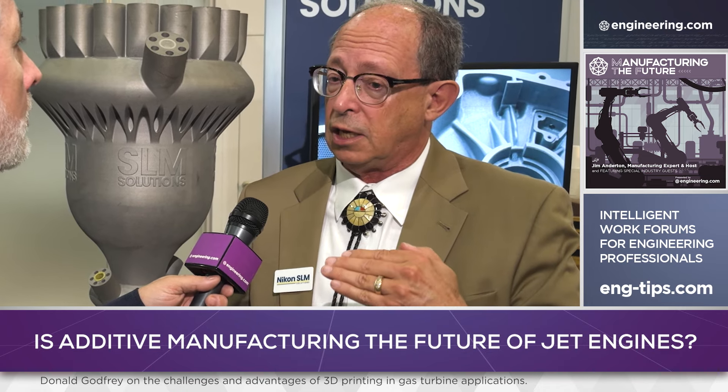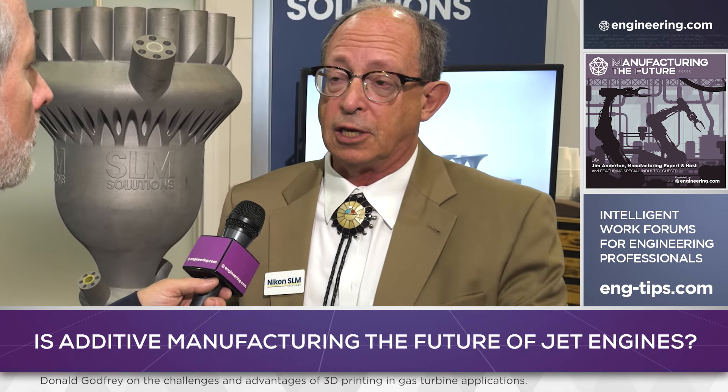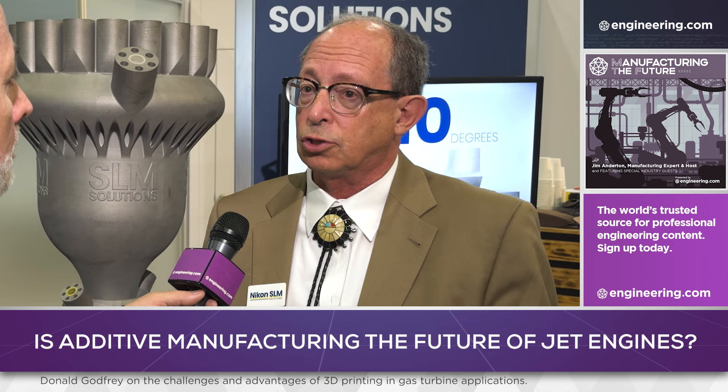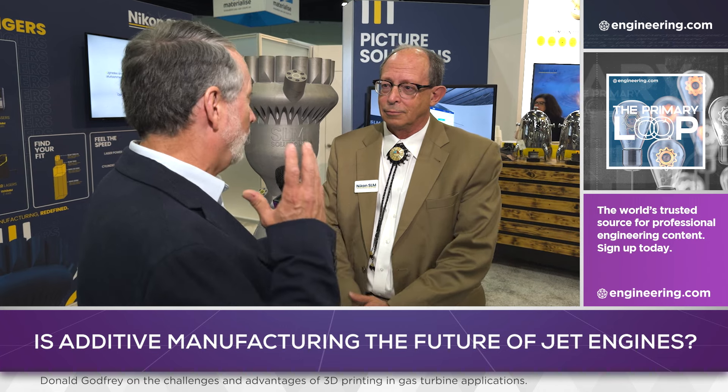Yes, it has evolved. Ten years ago it was not even thought of — printing a blade — because they were afraid of rotation causing a creep effect. But over time we've learned that concern can be controlled. Early examples had serious creep issues, we're talking about case contact in some cases. The seals people would say we're aiming for efficiency, we don't want leakage, we want to maintain clearances as closely as we can. Creep has always been a serious problem for the high-temperature guys, but now we're talking about production engines.